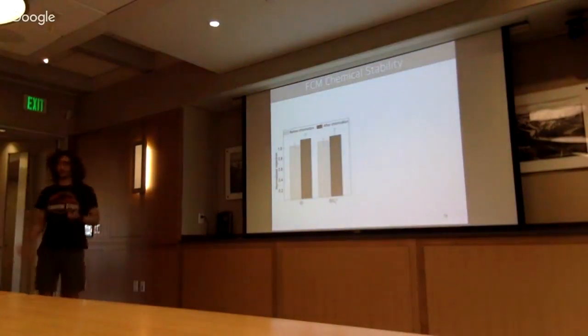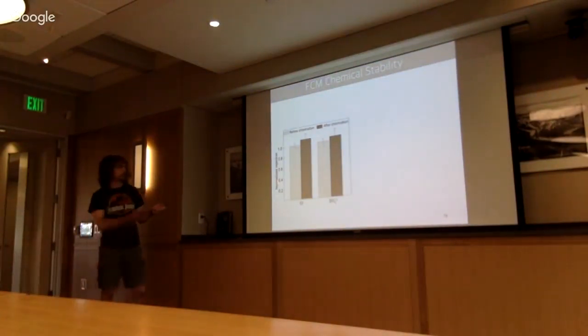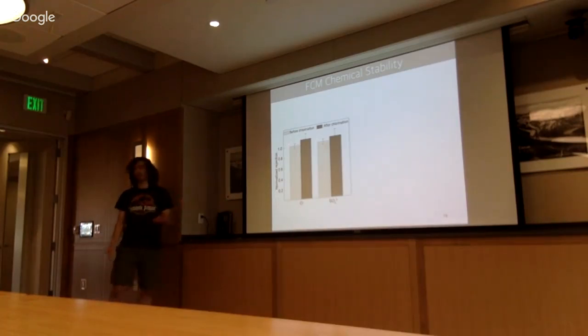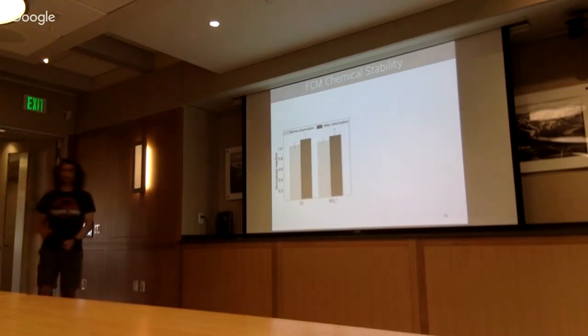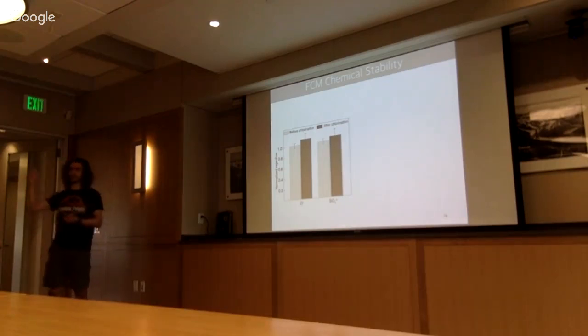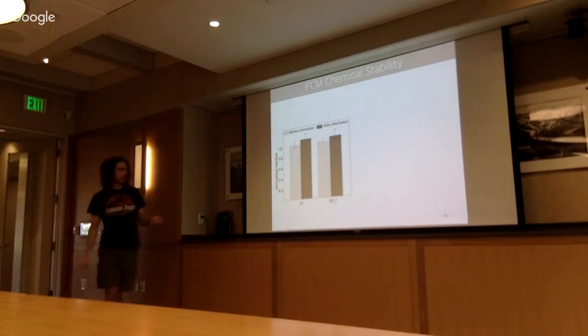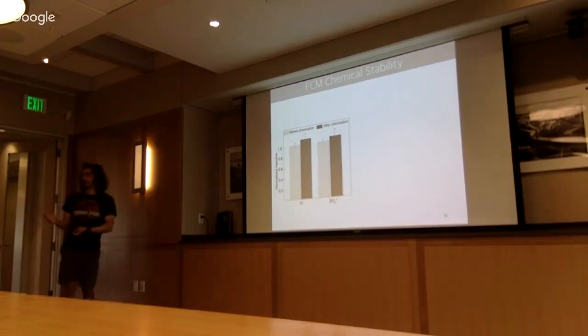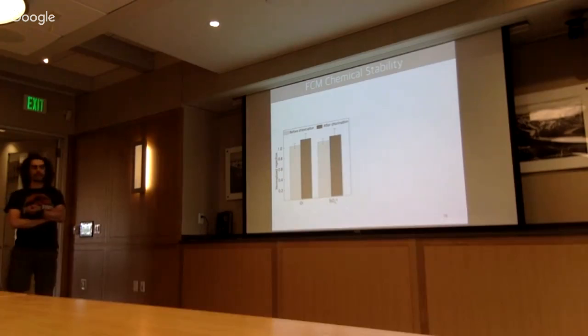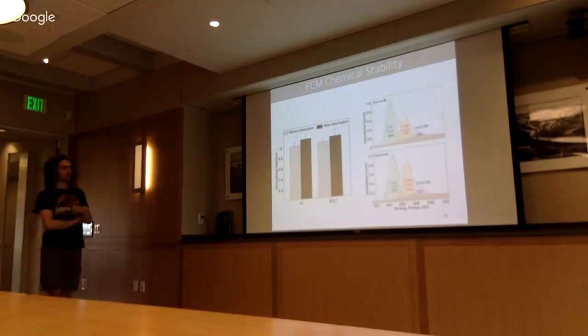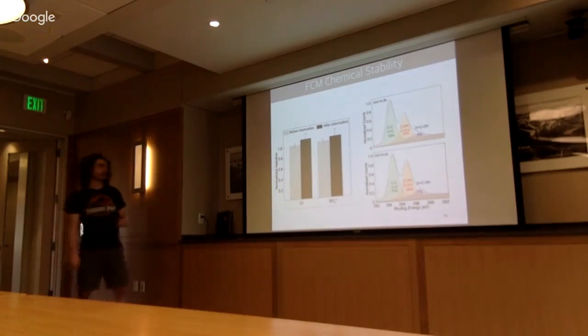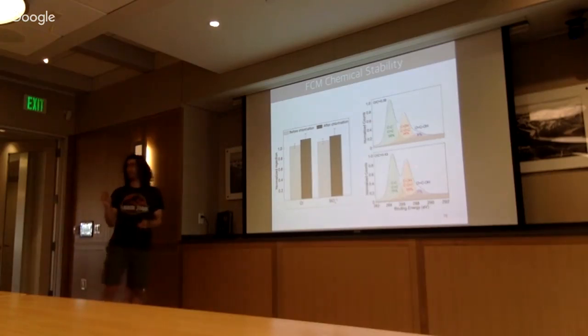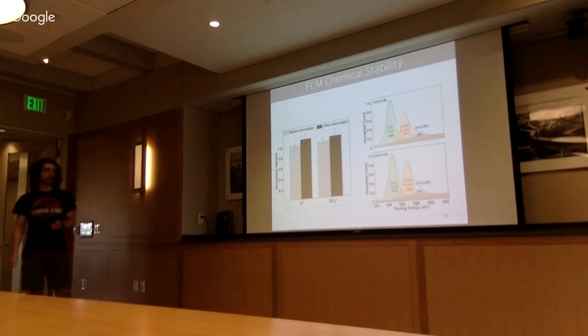However, we wanted to check their chemical stability. How we did that? Here I'm plotting rejection before and after chlorination. Chlorination is a method to check the stability of the membrane. What I did was run a highly concentrated bleach solution through the membrane for about 8 hours, and I'm checking the chloride and sulfate rejection. Before and after chlorination, it's basically the same. So this membrane can resist this chemical agent. We also checked through XPS the chemical fingerprint of the membranes. It's really similar. Maybe there is just a bit of oxidation happening in the membrane. So here we prove that the membranes are chemically stable.